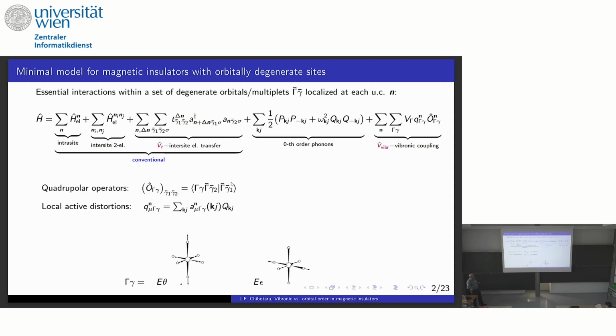These are the atoms around. They distort in the corresponding symmetrized form, and induce mixing between the local states. And because of this, we also have to include the entire phonon part, because the local distortions expand into phonons via the Van Vleck coefficients. So this is a known thing.